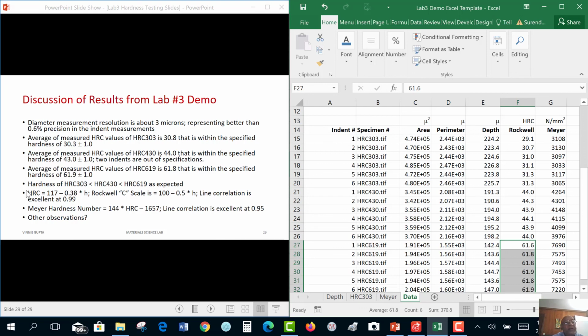Now we found experimentally that our HRC values measured by the machine, H measured or calculated through Fiji, follow this formula. Remember, our C scale is based on the H measured by the machine. So we are kind of there. We have 117 instead of 100, 0.38 instead of 0.5. Line correlation is very high. If we had many more measurements in all kinds of different ranges, we might have come closer to this.